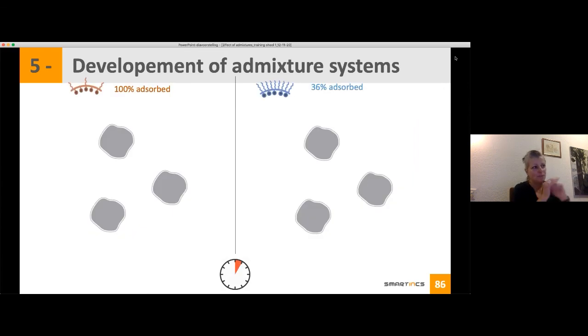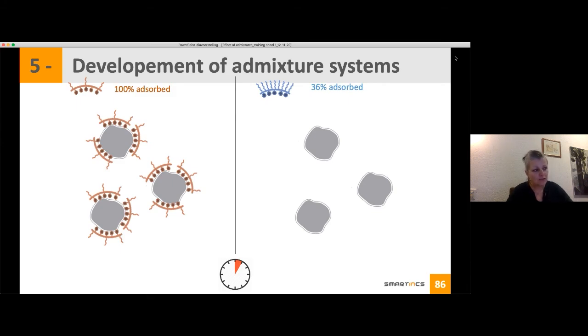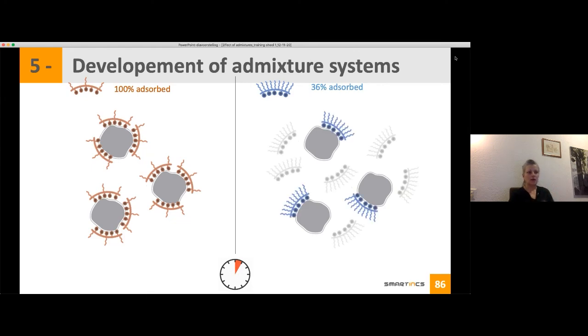So what happened? So here you have the two in parallel. On the left side, you see the red PCE, initially everything adsorbed. And the other one, you have a PCE that not a lot has adsorbed. So on the left case, it means, okay, everything I've put is on the surface of my cement, so there I get dispersion. On the right part, you say, okay, only a small fraction, the rest is somewhere in a pore solution and it has not yet functionality.